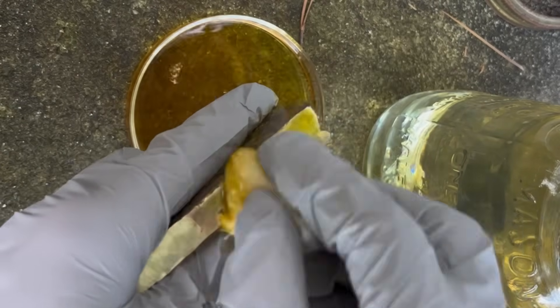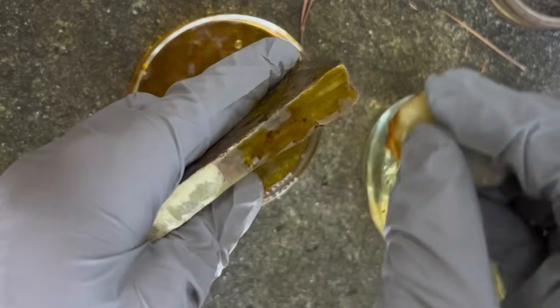So I etched both the ingots in some ferric chloride. After doing this the results were quite impressive. This is the alpha beta coexistence material and it looks extremely close to Widmanstätten. Under a macro lens we can see this even better. The raised regions are the alpha phase which precipitated out from the beta phase upon cooling which is the depressed regions. The alpha phase is raised because ferric chloride is etching the phase with more zinc composition. So beta is etched much faster than alpha. So our first etched material looks great.